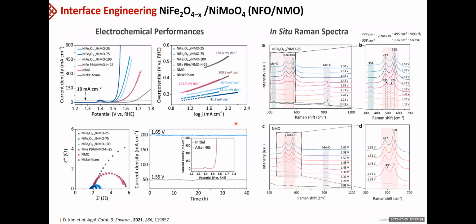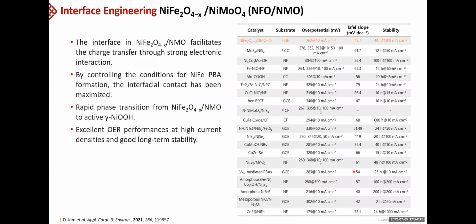We also studied the in situ Raman spectroscopy to understand what happens during this OER process. As you can see by comparing this pristine NMO sample and our sample, when we have this interface, the conversion of nickel oxyhydroxide species occurs at a lower potential compared to when you don't have this. So they actually contribute to the better OER performances. So we were able to tune the interface, the size of interface and the interaction between the two species, so successfully control their electronic interaction. As a result, we could achieve very good performance.